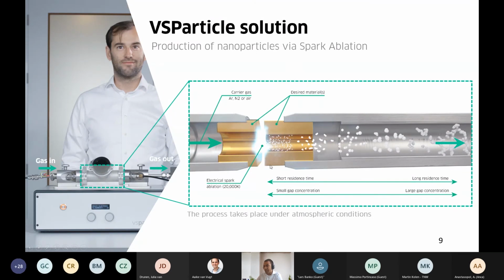We get the vapor of nanomaterial, and these then sinter to form larger particles. And what's unique about our technique is that we can vary the particle size by varying the residence time of the nanomaterial within this reactor head. So essentially, by varying the gas flow, we can vary the particle size. So higher gas flows generally produce smaller nanoparticles and vice versa.